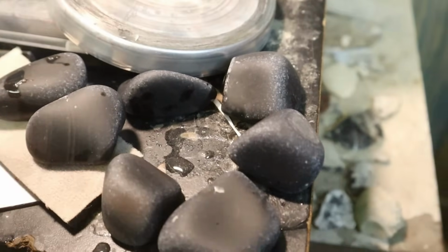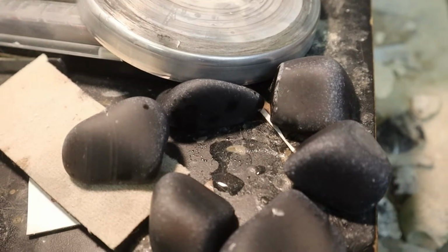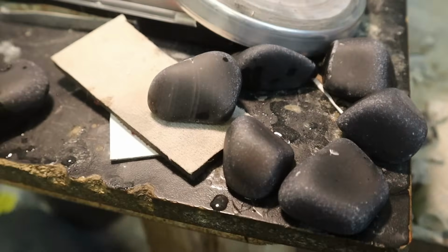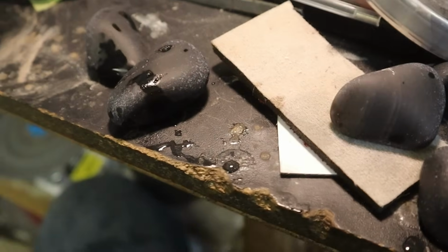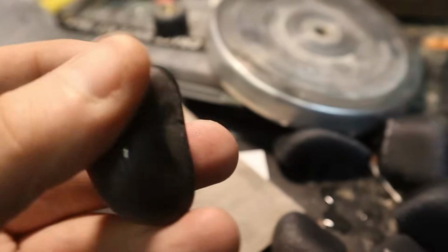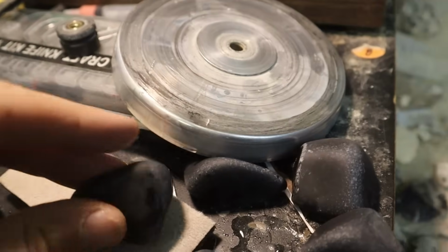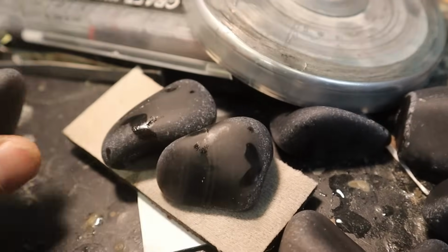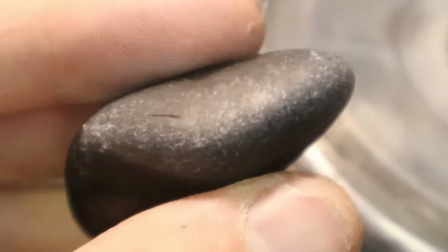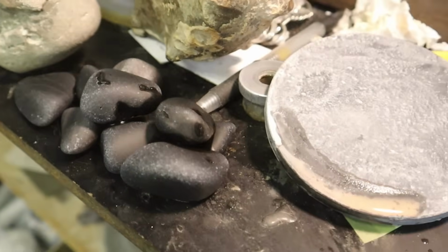So here's what I've whittled it down to. These are all of the really good sheens or rainbows, and even then I might take a few more out. We're gonna start back over at step 2, but we're gonna use way less grit, because all I want is to round off the edges. Flats actually look good. Flats are pretty much ready to go on. It's just those edges do not look good, and I think it is because it was overfilled. They were smacking into each other. It was creating all of these little micro impact dents, basically. So yeah, we're gonna need to get rid of those and start over. And I guess if it works, we'll put those in after everything else is done.